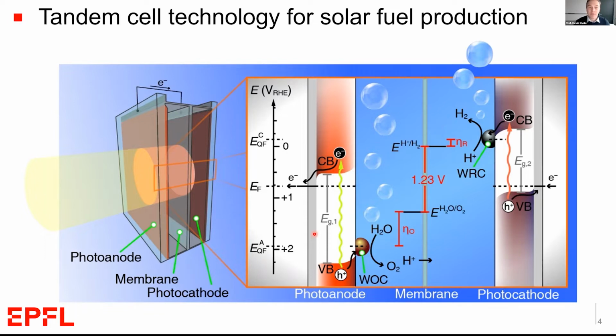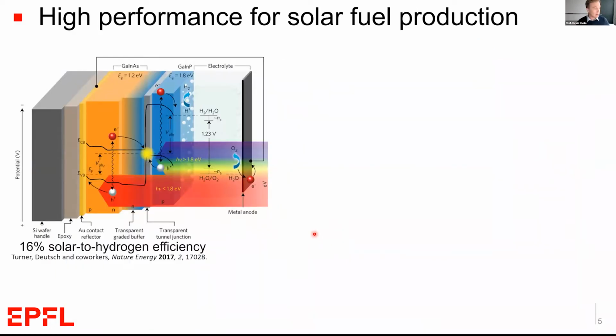Now, of course, our group is not the only group working on this. There are many demonstrations of many systems, and one of the highest efficiencies now is the system coming out of NREL in the United States, where Todd Deutsch and co-workers are applying these III-V type semiconductors like gallium indium arsenide and gallium phosphide in this kind of tandem cell and achieving very high efficiency solar to hydrogen conversion. However, the cost of these devices is prohibitively expensive. Indeed, something like this costs on the order of $10,000 for a small solar cell. So it's unlikely that this could ever be producing hydrogen at an economic cost.